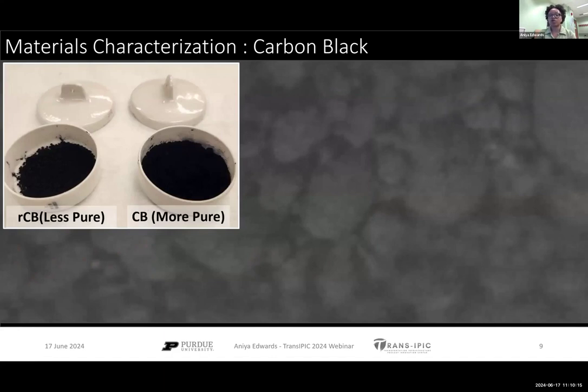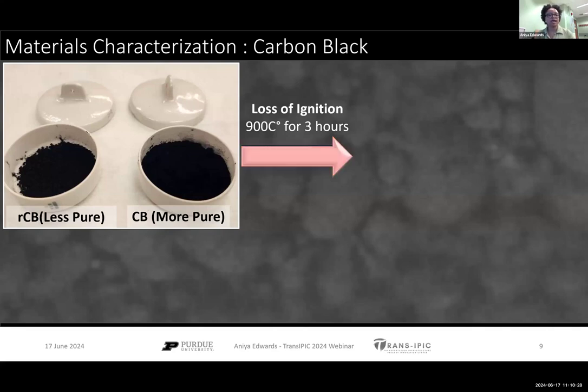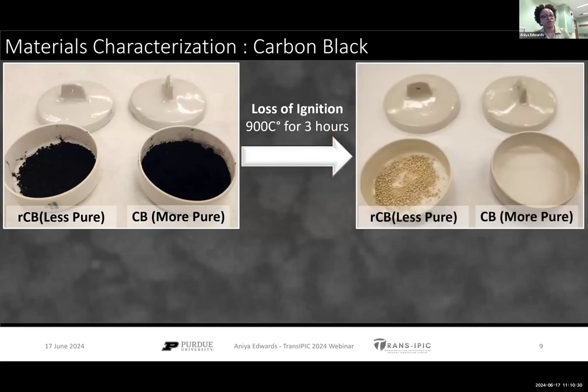Another thing to note about carbon black, so we're using recovered carbon black, or RCB. We have more pure carbon black, which comes from those hydrocarbons that I mentioned earlier. And when doing a loss of ignition test, we heated up our 2 different carbon black samples at 900 degrees Celsius for 3 hours. And what we found was that the more pure carbon black completely disappeared after that heating. So that shows and affirms its purity, whereas the less pure carbon black, which was made from the waste tires, has impurities left over, not necessarily carbon.